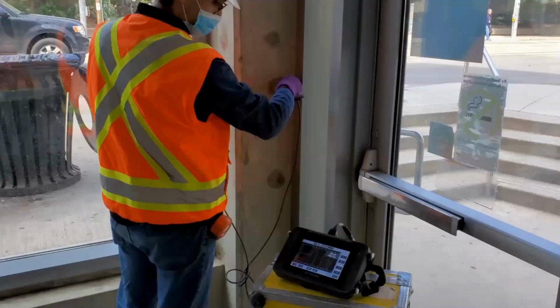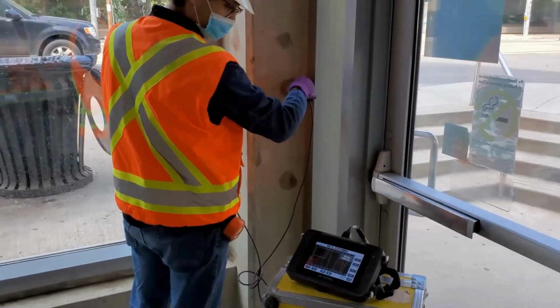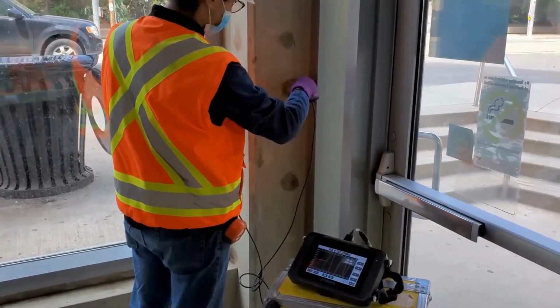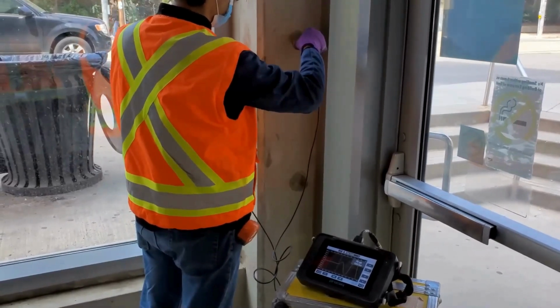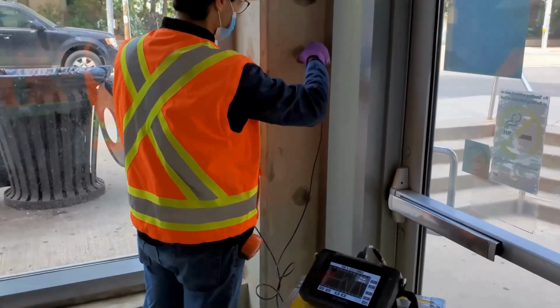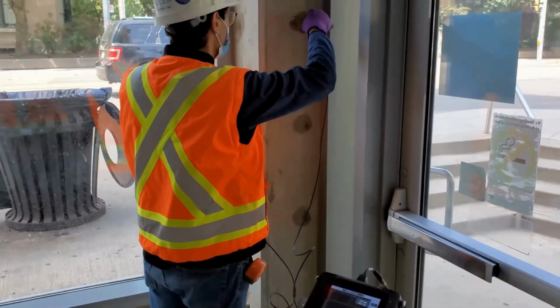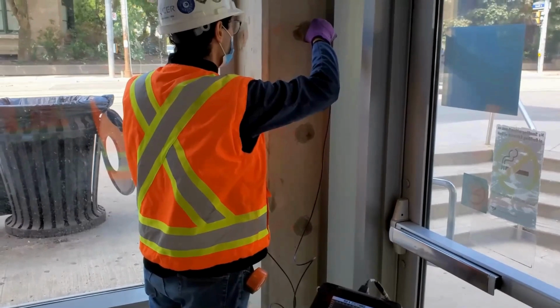In the next slide, I'm just going to show you visually how the test looks in a practical setup. As you see, here we are testing a concrete column, and we want to see if ultrasonic pulse velocity can show us if there are any major defects in the concrete element. And in this one in particular, we are not doing conventional laboratory UPV. We are doing it in a field setup, and we expect that the presence of steel reinforcement might have some influence on the readings. So we want to extend the test beyond its limit to see how far ultrasonic pulse velocity can go in providing information about the quality of concrete and also the presence of potential significant voids or defects.